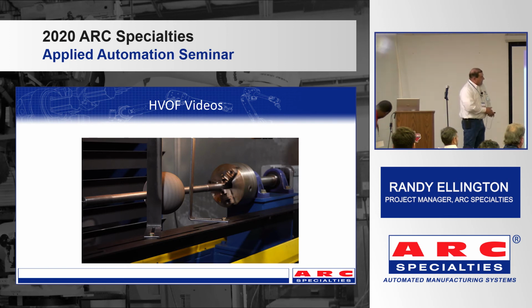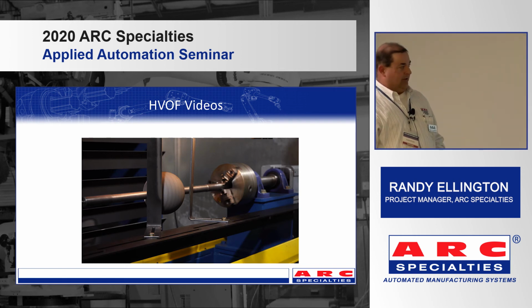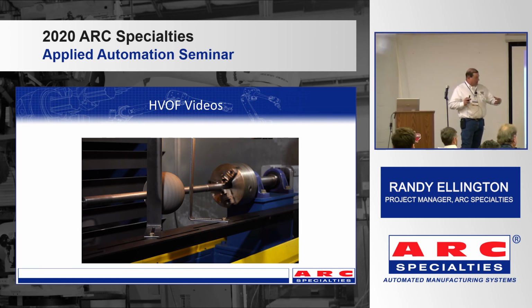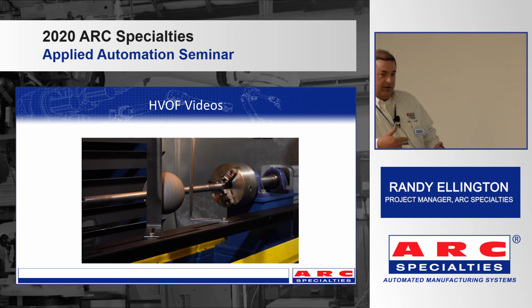Okay. Here you see the robot come on, and we're traversing across that part. Looks real simple, and it relatively is. But what you've got to be concerned with is the difference in surface area. On the two ends of the part, close to the flow bore, you've got a smaller diameter, and in the middle, you've got a larger one. So to put that coating on evenly around the outside, you need to travel fast and then slow down and then come up fast again and come off the part without staying anywhere too long and building up heat.